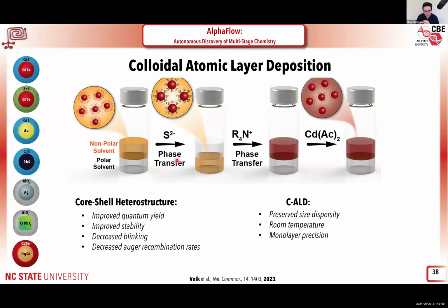Where you can start with a semiconductor core, and then you can grow a shell around this core layer by layer. Now, each layer has 2 half cycles, and you have to wash your product after every half cycle. This is a very powerful technique because it maintains the size distribution of your nanocrystals. It improves the optical properties of these nanocrystals through passivation, and it can even introduce new optical or magnetic properties into your core nanocrystals. So it's very powerful, but it's very tedious and difficult to perform because you have 10 different layers, 40 different knobs that you have to tune. So it's a huge dimensional space.